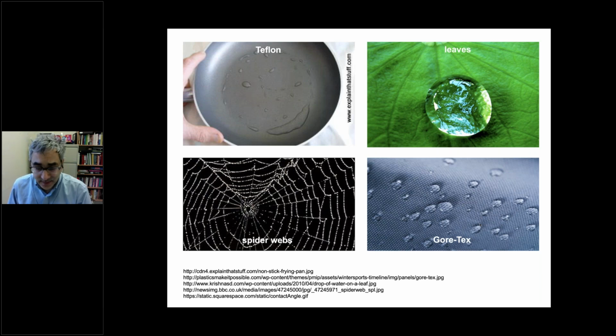In the opposite case, the classic example of hydrophilic is a very clean piece of glass. If you have a horizontal piece of glass that's super clean and you put a drop of water on it, it'll spread to cover the whole glass. One of the reasons people are so interested in hydrophobicity when it comes to silicon insulators for power line applications is that it's understood to be one of the reasons why the materials have such good and prolonged performance. It's been noted in the field that once the hydrophobicity starts to decline, this eventually leads to water ingress and the premature end of life of these insulator materials.